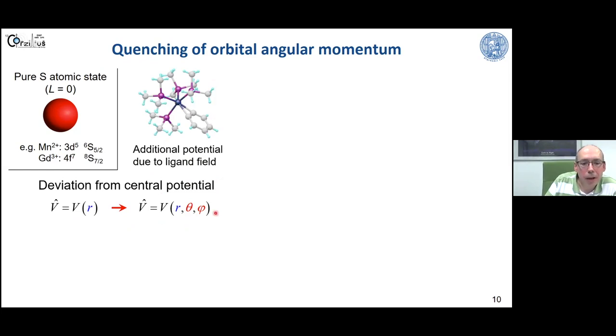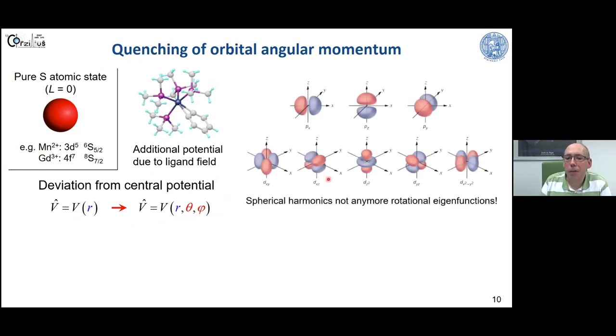So this introduces an angular dependence of the potential. In this case, the spherical harmonics are no longer rotational eigenfunctions. Now we can look at these wave functions again, and this is what we know practically from our chemistry class. We have the px, pz, and py orbitals, and the dxy, dxz, dz squared, dyz, and dx squared minus y squared. These are all linear combinations of our direct solutions of the Schrödinger equation for the hydrogen atom. The linear combinations are such that these orbital lobes point towards the ligands or just in between two ligands. With this, you can minimize the total energy of your electronic state.